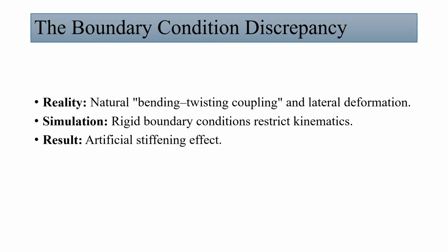The ANSYS results were accurate for the 0° and 90° symmetric layups. However, for the off-axis layups, like the 45° ones, ANSYS predicted they were much stiffer and stronger than they actually were in the lab. Why did this happen? It's because of the boundary conditions.